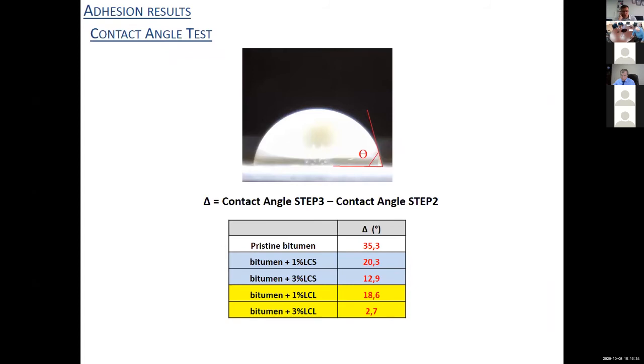To evaluate the adhesion, the difference between step 3 and step 2 is calculated. We have a good adhesion when the contact angle in step 3 and step 2 is equal or very similar. The greater the difference between the 2 steps, the worse the adhesion. Because in step 3, the effect of the water with the melted bitumen increases the angle if there isn't a good interaction between stone and bitumen. While in step 2, we record a lower angle, better adhesion, because the sample is prepared in optimal condition without water.